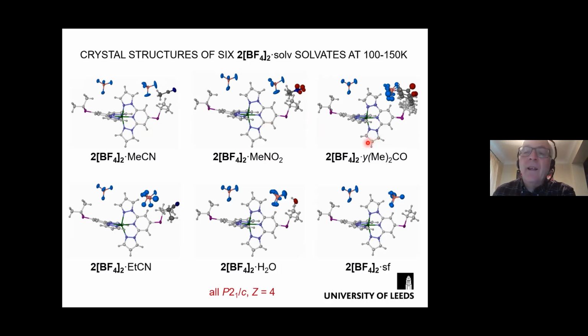I should say that we can interconvert some of these by single crystal to single crystal transformations. So you make the water solvate, for example, by heating the acetone solvate for 2 days in an oven. It loses the acetone and then absorbs water in air. The crystals stay good and you can measure them. And then if you heat the water crystals on a diffractometer, you can remove the water and make the solvent-free crystals with no solvent at all. But the crystal structure is always the same.